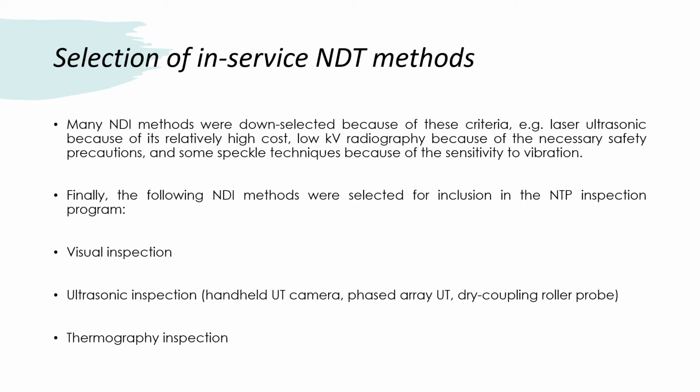Now coming to the selection of NDT methods. Many NDI or NDT methods were down selected because of criteria: laser ultrasonic, because of its relatively high cost; low kilovolt radiography, because of the necessary safety precautions; and some speckle techniques because of the sensitivity to vibration. Finally, the following non-destructive inspection or NDI methods were selected for inclusion in the NTP inspection program: visual inspection, ultrasonic inspection and thermographic inspection.